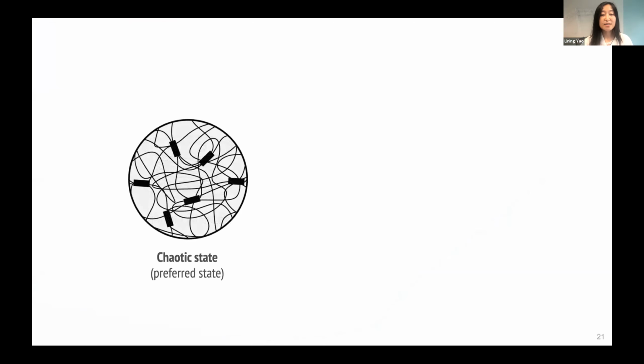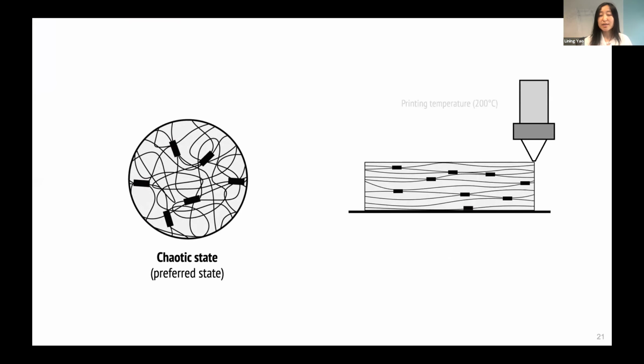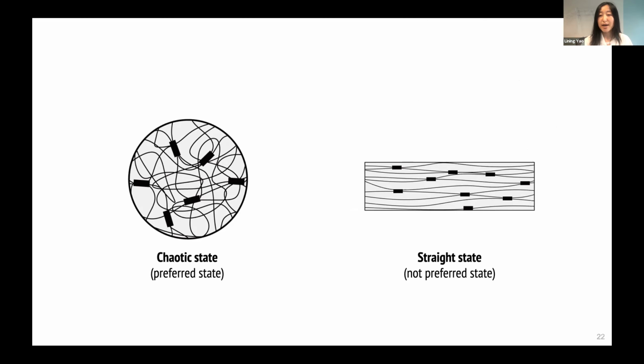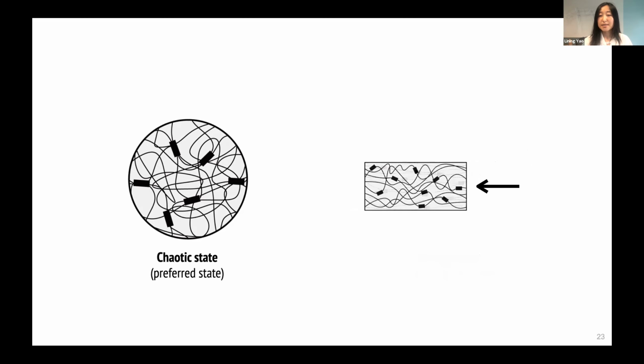A bit of the mechanism behind it: for polymers like PLA and ABS, the polymer chains like to stay in a random mode when you buy them off the shelf. However, when you melt it down and extrude it on a printing substrate, you're pretty much straightening the polymer chains. This is not the energy-preferred state. So what happens is if you print too fast, the polymer chains will basically recover back to their random mode. And that really causes the warpage and the lifting off from the substrate.